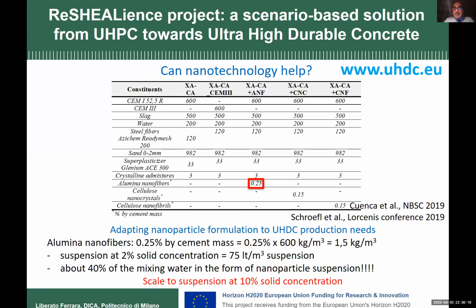But as a matter of fact, the problem is the dispersion of these nanofibers. On the market — which was not really for construction, but for other industrial applications — these nanofibers came in a suspension at 2% solid concentration. So in order to have 1.5 kilos of nanofibers, you would need 75 liters of suspension.